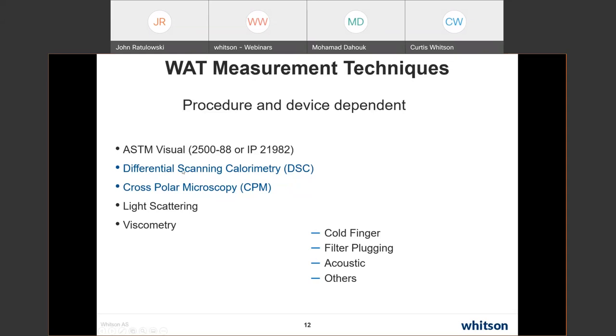So both the DSC and CPM are somewhat geared towards the crystalline wax, but luckily, the normal paraffins are usually what control the wax appearance temperature. So it's not a huge issue that these are not looking at the microcrystalline waxes.